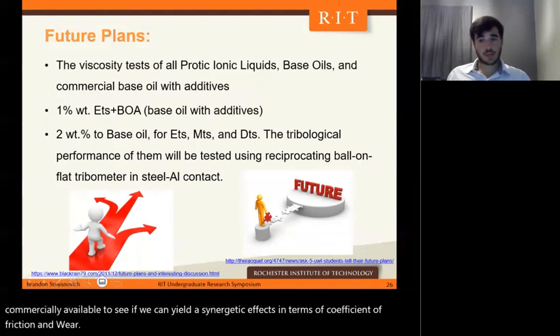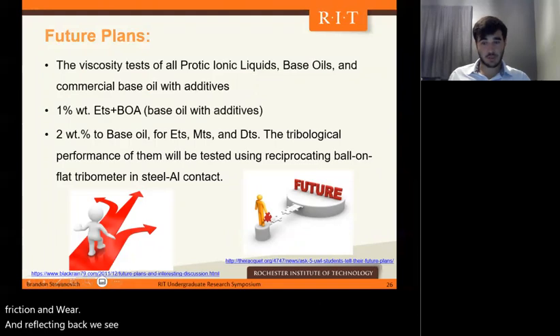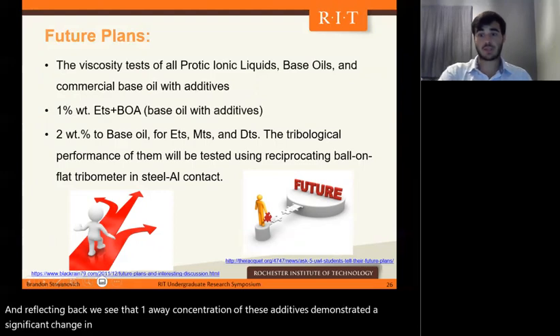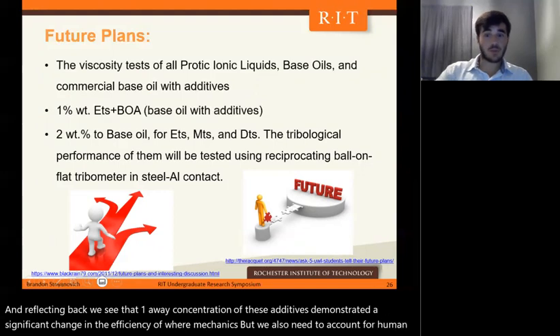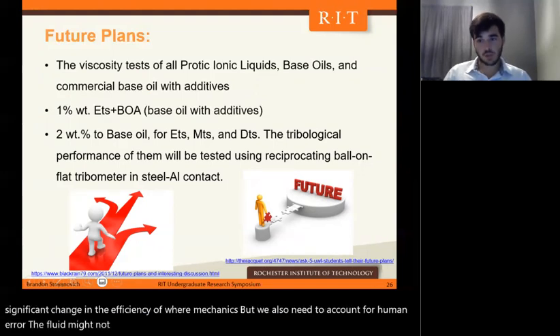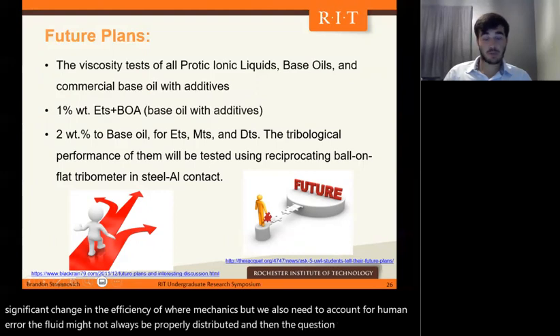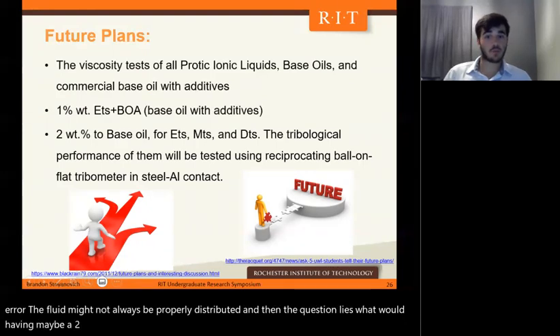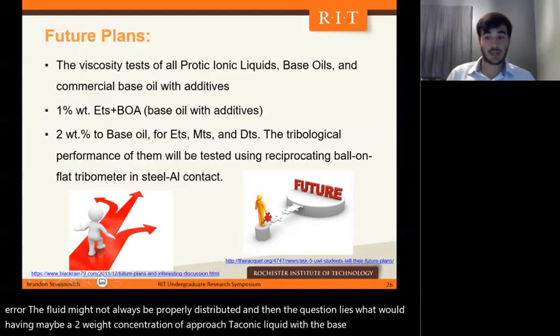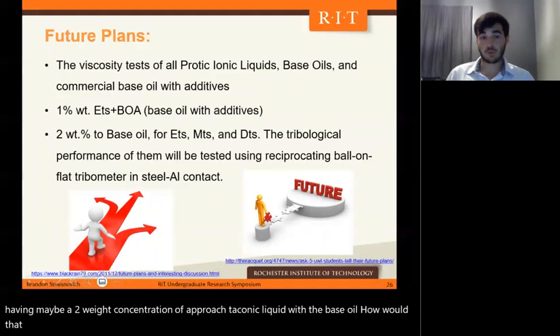And reflecting back, we see that 1% weight concentration of these additives demonstrated a significant change in the efficiency of wear mechanics, but we also need to account for human error. The fluid might not always be properly distributed, and then the question lies, what would having maybe a 2% weight concentration of a Protic Ionic liquid with a base oil, how would that impact a ball and disc for aluminum steel contacts in the future?